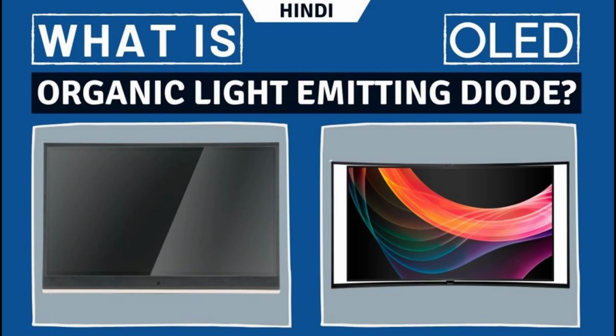In particular, blue OLEDs at that time had a lifetime of around 14,000 hours to half original brightness, 5 years at 8 hours per day, when used for flat panel displays. This is lower than the typical lifetime of LCD, LED or PDP technology, each rated for about 25,000 to 40,000 hours to half brightness, depending on manufacturer and model.